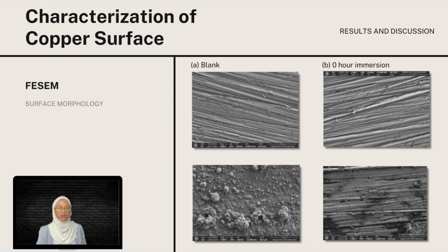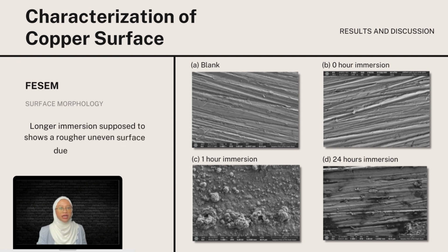However, after 1 hour, the copper surface has started to react with artificial sweat solution, and the deposited materials on both 1 hour and 24-hour samples most likely come from the reaction with the solution. Therefore, longer immersion time showed a rougher, uneven surface due to less resistance to corrosion. In any case, in order to determine what kind of material is deposited on the surface, XRD or EDX analysis may be employed.